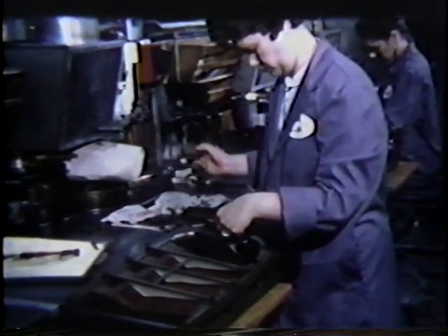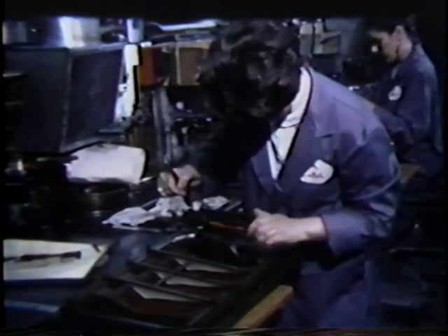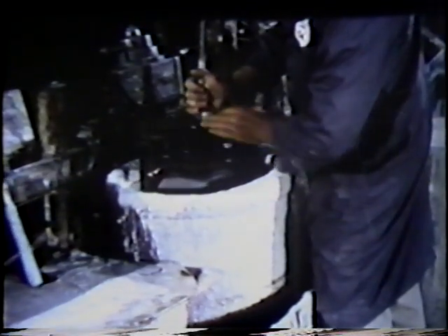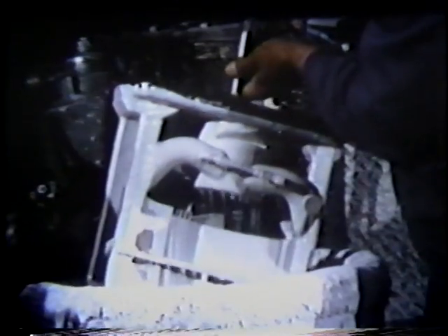The state of the art in investment casting was extended in casting size, complexity, and the ability to provide thin sections and narrow, deep cooling channels. Following build, the wax assembly is used to form the final ceramic mold or shell in which the casting will be made. During the dipping process used to make the ceramic mold, the first coating of slurry is of extremely fine zirconium material to ensure adhesion of a thin layer to the entire wax surface.